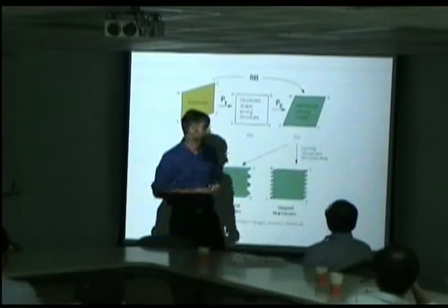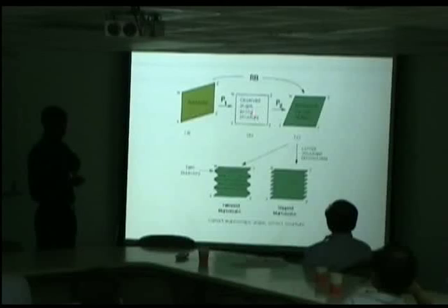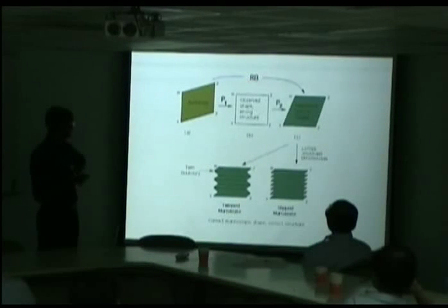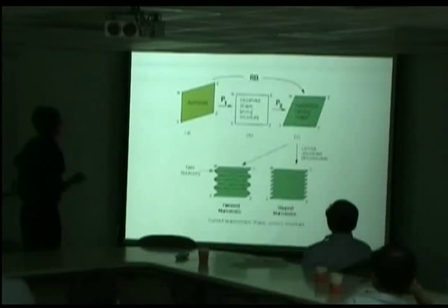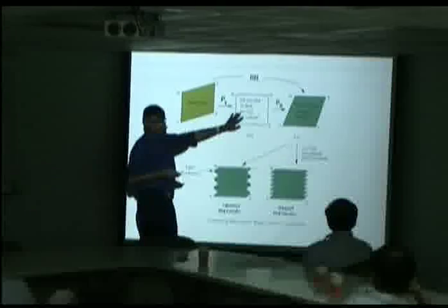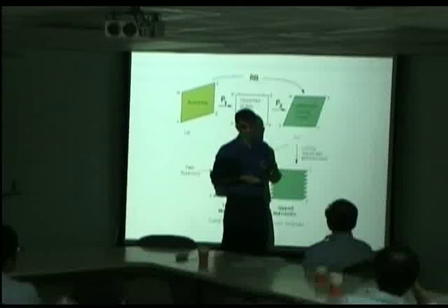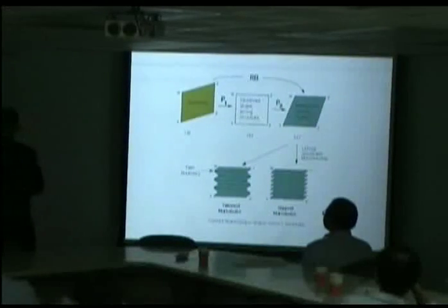But then I have the wrong shape. Yeah? So I can either get the right shape and the wrong crystal structure, or the wrong shape and the right crystal structure. To go from austenite to martensite, I have to have a combination of the Bain strain and the rigid body rotation, which is not a shear. Nevertheless, when I observe the shape change, I have this, not this. Okay? Now, the problem was solved by Bowles and Mackenzie.